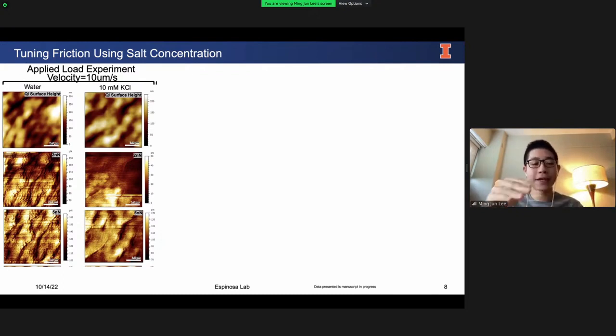And then from the second and third row onwards, these are friction maps. So direct visualization of the friction force on the surface of the hydrogels. First experiment I'll be showing is the applied load experiment, where I have fixed the sliding velocity of the AFM tip to 10 microns per second.